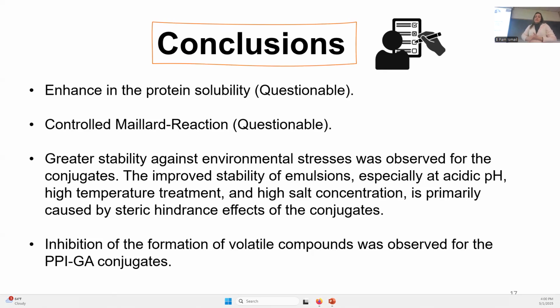The greater stability against the environmental stress was observed for conjugates. This is questionable too, because we barely see any difference in the particle size. And the difference was attributed to the steric hindrance effects of the conjugates. And then they saw an inhibition of the formation of volatile compounds for the PPI conjugates.